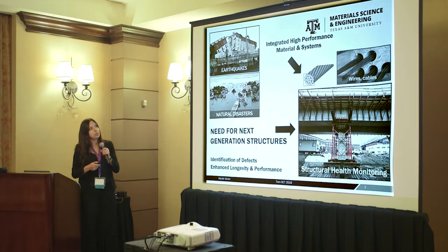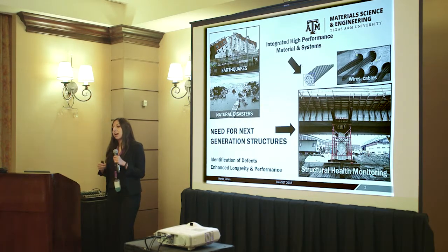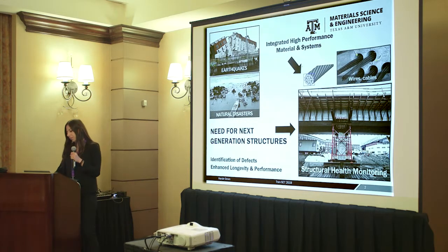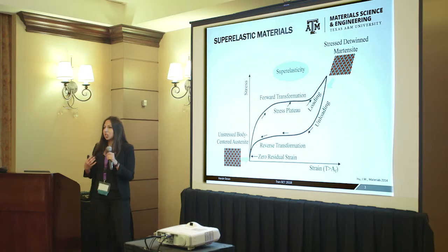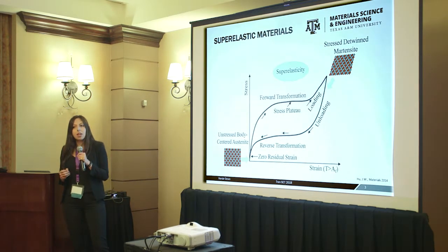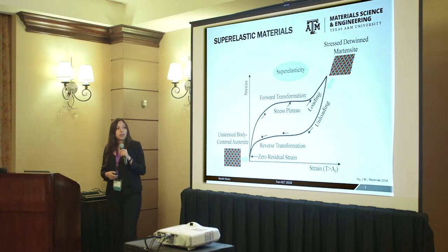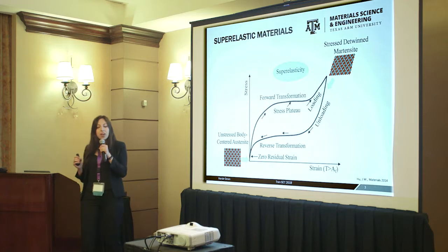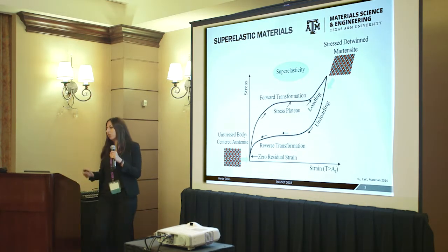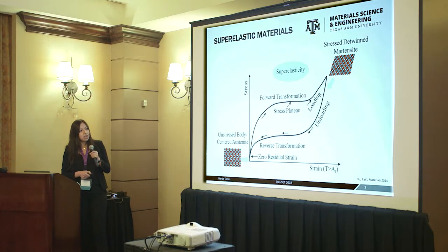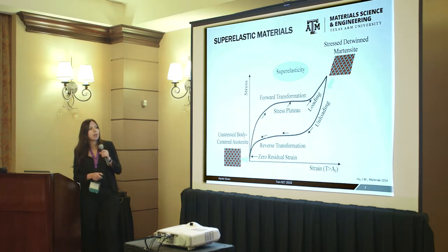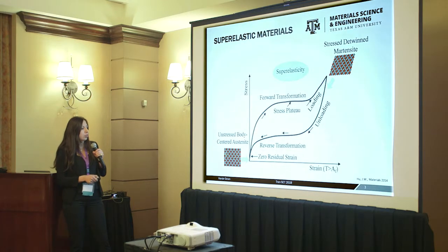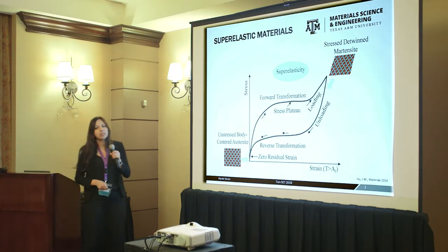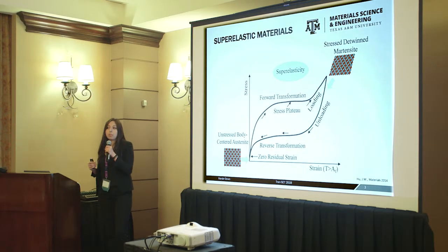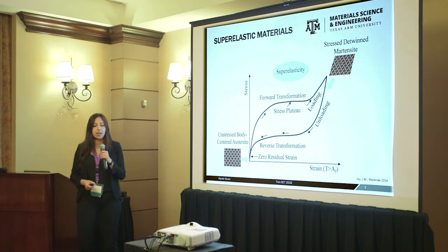One way to do that is to integrate high performance materials and systems into the structures. This can be achieved by using a shape memory alloy. These shape memory alloys are a special class of alloys that can recover a huge amount of strain compared to conventional stainless steel alloys. These materials go through a solid-to-solid phase transformation. Here, this is a typical superelastic shape memory alloy. They go through a solid-to-solid phase transformation from austenite to martensite, and this phase transformation can be triggered by stress. When it's triggered by stress, we call this superelasticity.